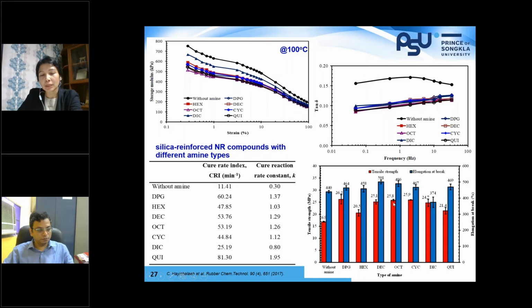And if we look at the mechanical properties in terms of tensile strength and elongation at break, if we see DPG here and other types of amine, you can reach a similar level of tensile strength by utilizing this octadecylamine, cyclohexylamine, and also DEC. So different amines can be used in replacement of DPG, and we can still obtain similar mechanical and also dynamic properties. We investigated different compound properties before and after vulcanization, but I select some results to show you here, just to give an idea that if we don't want DPG in the compound, you have something else to be chosen.